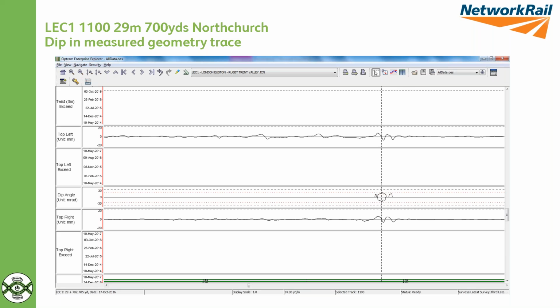You can see on the dip angle trace, there's nothing else around it. It's not riddled with this type of fault. It's quite a localized effect, and that's quite common on a lot of main lines, and perhaps not a problem in younger rail, but when we're starting to run higher cumulative tonnages, this rail was an older rail, perhaps something between 1,000 and 1,500 million gross tons. So American billion, 1.5 billion tons over it, but generally in reasonably good condition, except for this local spot with a dip angle. So one of the challenges is to look at what other information we have that may give us a clue to these locations and the risks they present.